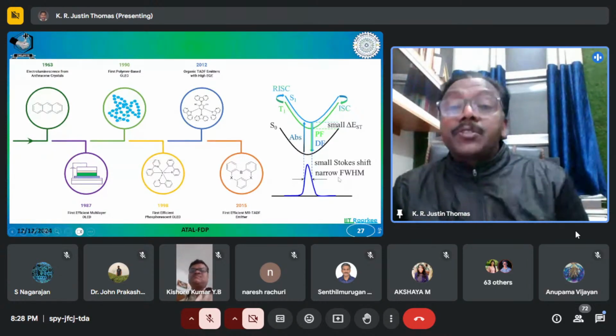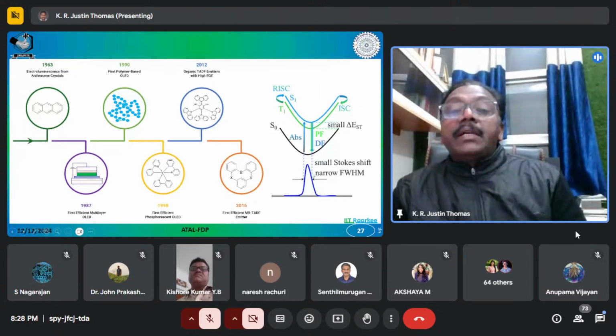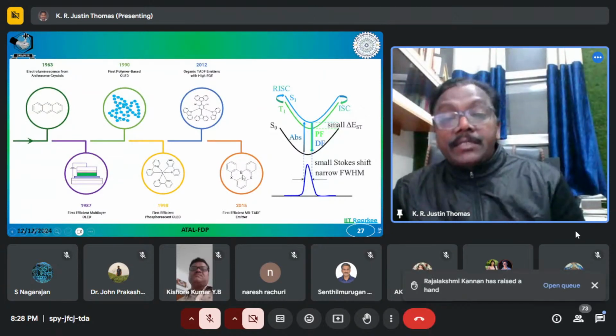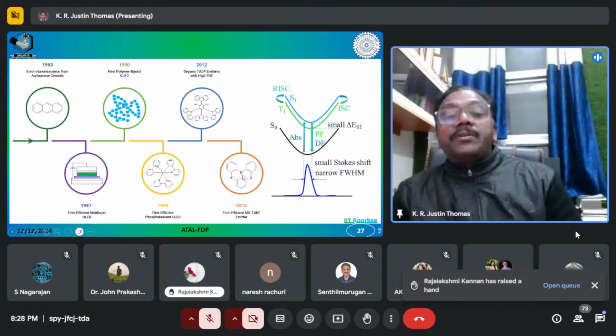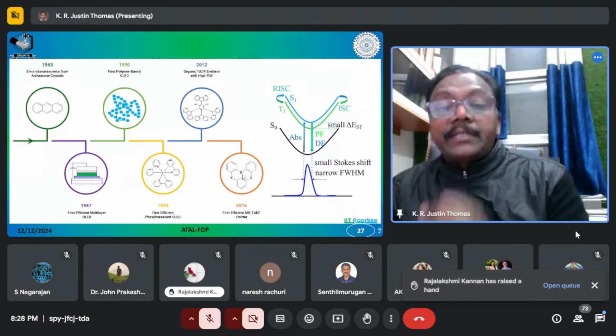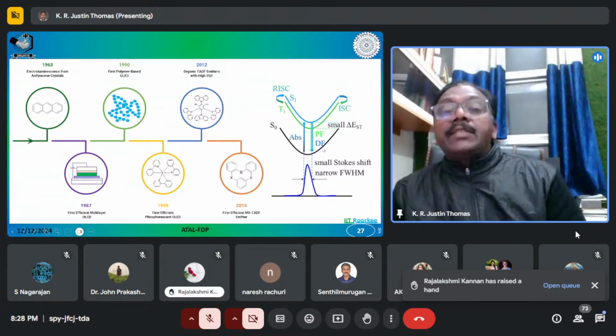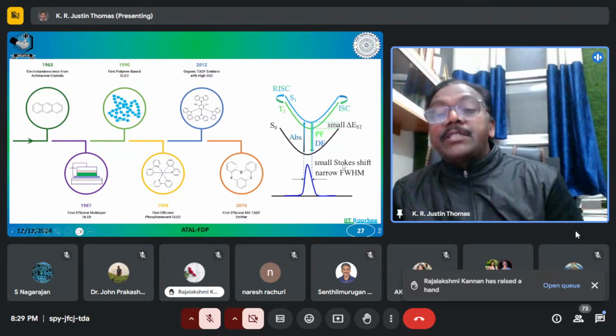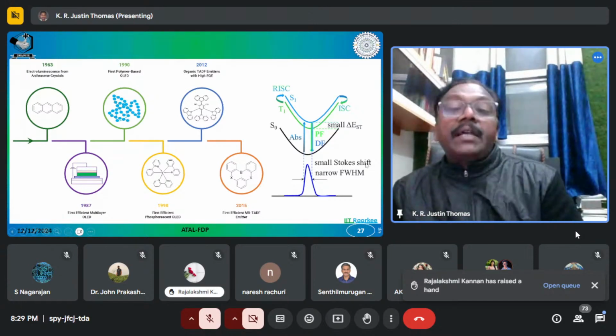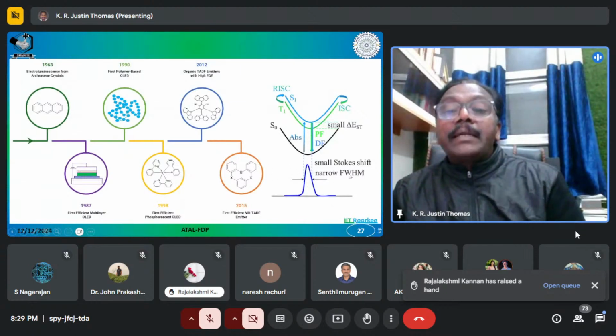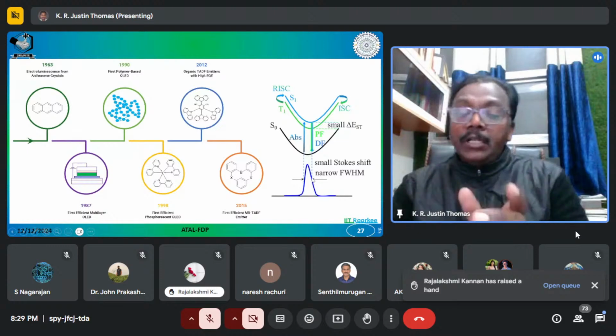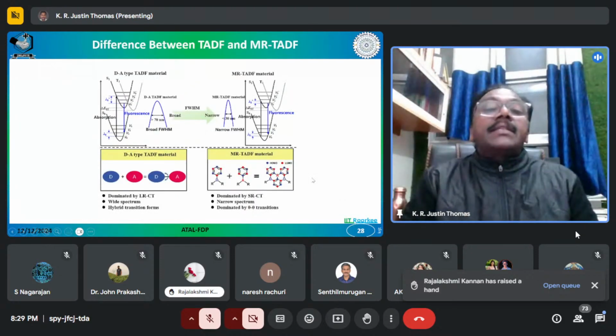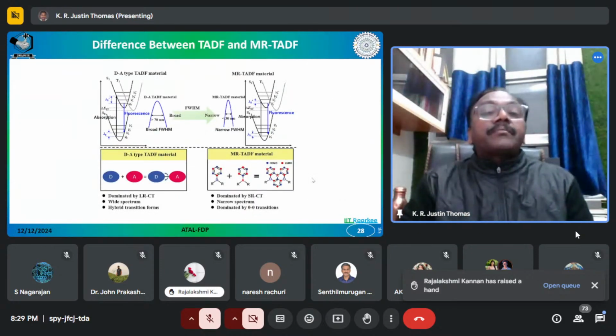That is mainly because of the small Stokes shift. And it is rigid. Because it is rigid, it will not undergo reorganization during an excitation. And since there is no reorganization, the absorption and emission wavelengths are closer to one another, which leads to a small Stokes shift. And that leads to a narrow full width at half maximum in the emission. So you can look at this one and understand this even better.